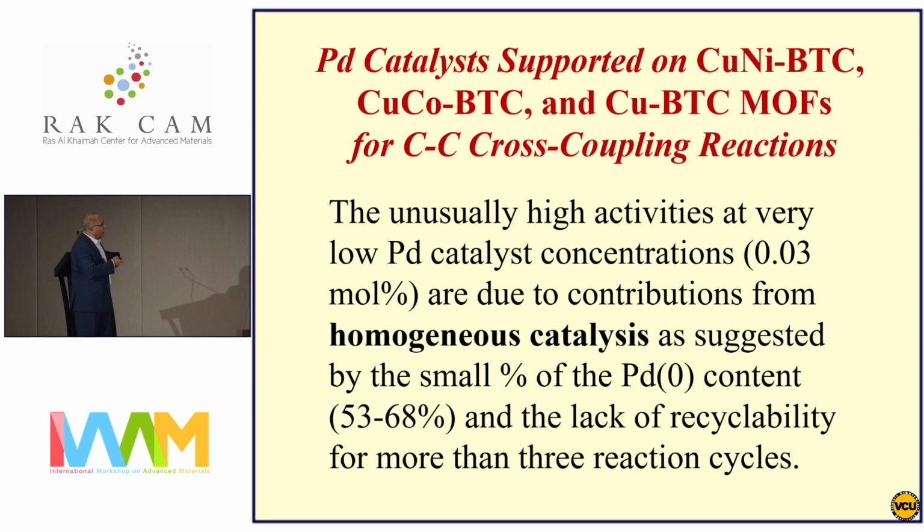And also, that's suggested by the low palladium content, which was evident from the XPS analysis. So this system actually turns out to be mixed between palladium ions activating the reaction and the palladium nanoparticles together activating the reaction.